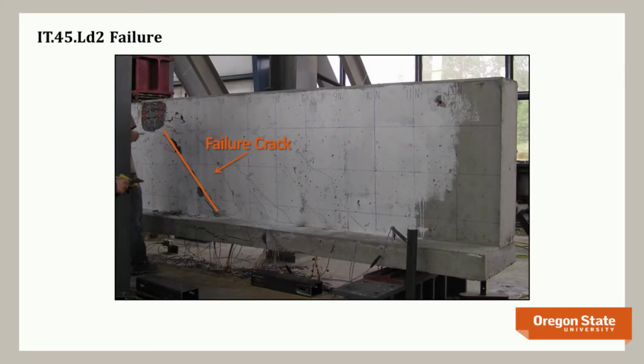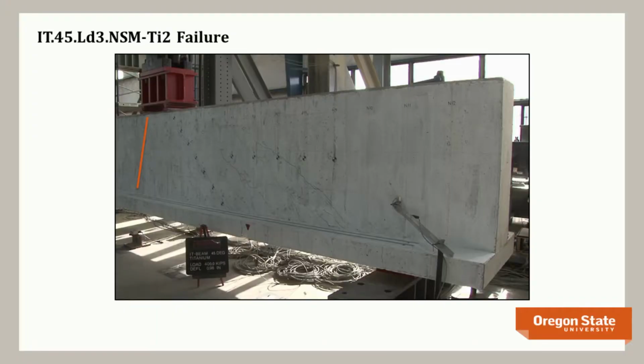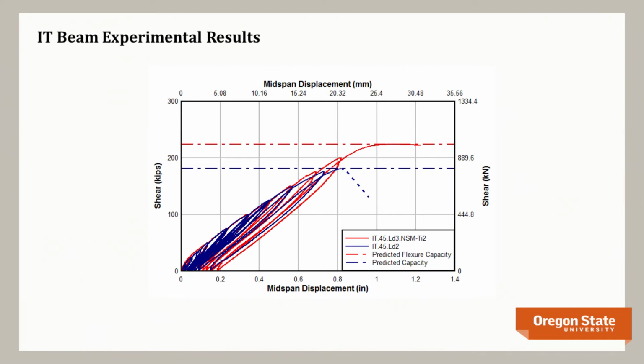Here's a picture again. This is a control specimen. Fails because of the tension anchor. This is a negative moment region. Rather than push up, we just roll the girders. So we're producing a negative moment with high shear. And again, we put in our titanium bars in the soffit of the deck, and we move the failure mode into a ductile failure mode at the end of the bars. Again, control in blue. With the titanium, we get that nice ductile behavior.